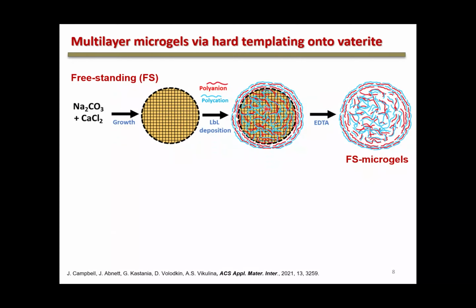In this case, they are porous particles, so adsorption occurs inside and on the surface of the particles. So first a layer of polyanion, then polycation, polyanion, polycation. You just alternate positively and negatively charged polymer in sequence until the number of layers you wish is reached. So basically you introduce inside the pores of the particles a polymer complex with different charges.